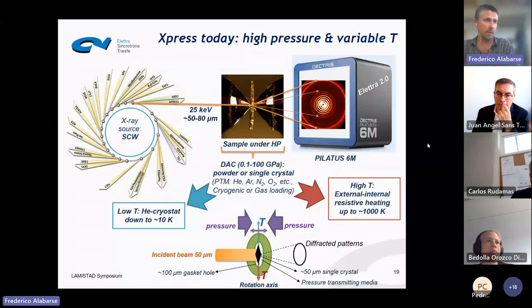As a pressure transmitting medium, some users can load the sample with helium by gas loading or some other fluids by cryogenic loading. We can go down to 10 Kelvin using a cryostat. This means high pressure together with a cryostat, low temperature, and or high pressure together with high temperature by resistive heating. If you want to go beyond this pressure range or temperature range, you can go to other instruments around the world, in Europe, or other synchrotrons.